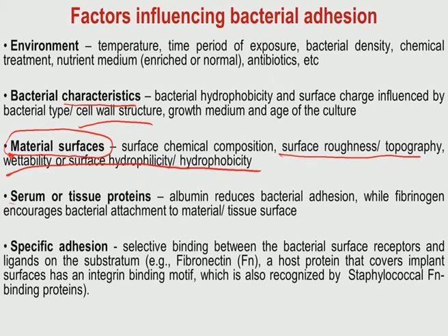Mostly, if you coat the bacterial biomaterial with certain albumin proteins, that typically reduces bacterial adhesion. But if you coat them with fibrinogen, that essentially encourages bacterial attachment to material surfaces. So, it does not necessarily mean that all proteins have repelling properties towards bacterial adhesion. In fact, some of the proteins can encourage more and more bacterial attachment, which should be avoided.